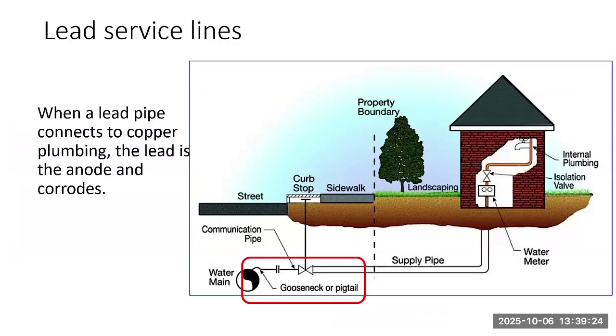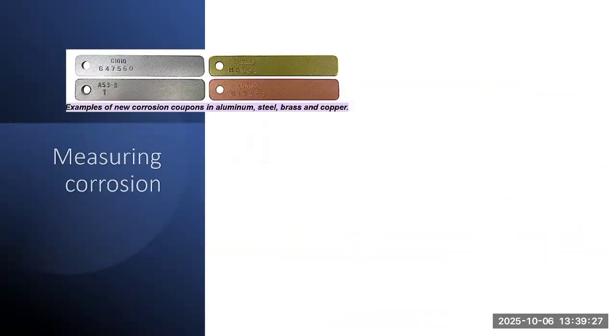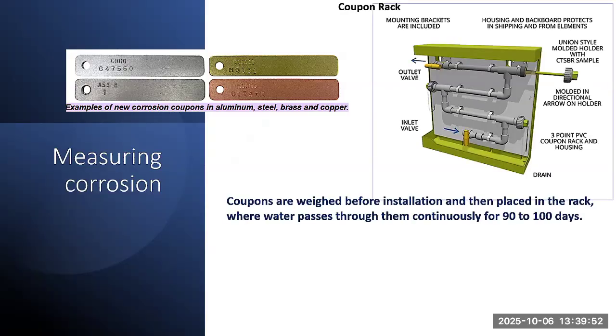To measure corrosion, we can use coupons. And here's different kinds of coupons here. We have aluminum, steel, brass, and copper. And the idea is that the coupon is the same material as the plumbing material or main material that we're trying to protect. And so we can actually have a coupon rack that contains the different types of coupons, and we can allow our drinking water to flow through those coupons and let the water flow for 90 to 100 days, then take them back out and weigh them and see if they've lost any weight. And so the coupon has to match the material that you're trying to protect.